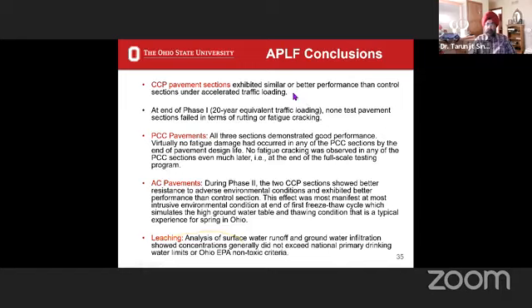Here is what our conclusions were of the project: that the CCP pavement section exhibits similar or better performance than control under accelerated loading. At the end of phase one, that is 20 years of traffic, none of the pavement sections failed. In terms of rutting, rutting would be applicable to asphalt, fatigue cracking to concrete. So it did not fail in phase one.